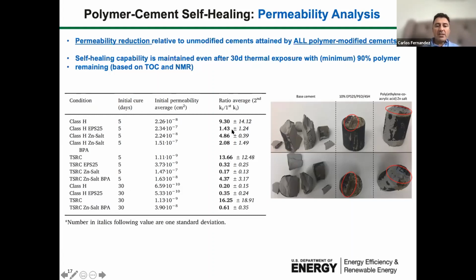But if you have a polymer, in some cases you still have a permeability that is higher than the original fracture, but it is much lower than the unmodified cement. And of course, in most of the cases for the TSRC, for example, we have a permeability that is reduced by 70%, in some cases almost 1/8 of the original permeability. So you can see the self-healing behavior taking place, and you can also see it by naked eye. We have also presented some X-ray microtomography to show where the polymer is located, and you can not only see the polymer homogeneously distributed in the cement, but also that it has migrated to the fracture and generated a bond with the fracture, completely or at least nearly totally filling the fracture.